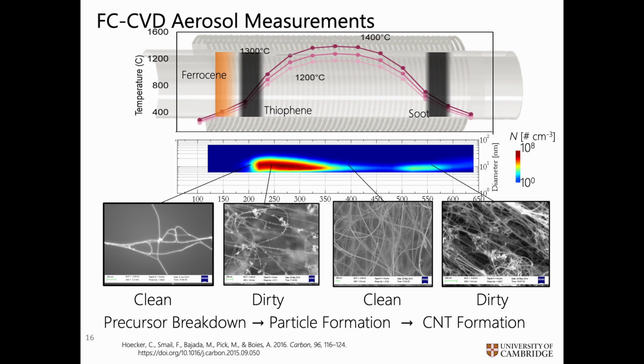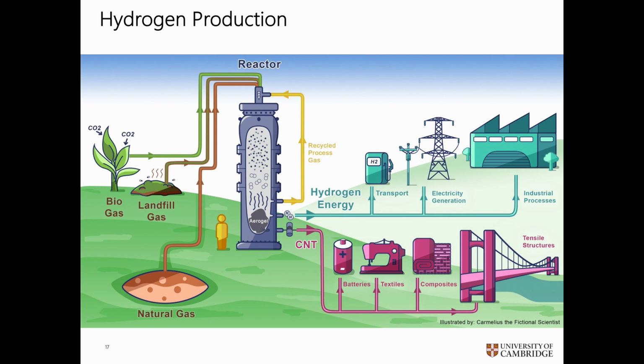So one thing that I showed you here is that this is a single pass. And the real dirty truth of this entire field is that everybody has been running hydrogen through on a once-through basis. And so we've actually been net consumers of hydrogen, not net producers, because we're not looping the process around. Nominally we're 90% hydrogen here, and if you're only passing hydrogen through once, you're not being very effective with your hydrogen. So a big result for us fairly recently, in the last, say, year and a half, has been that we've shown we can recycle these species and net produce hydrogen.